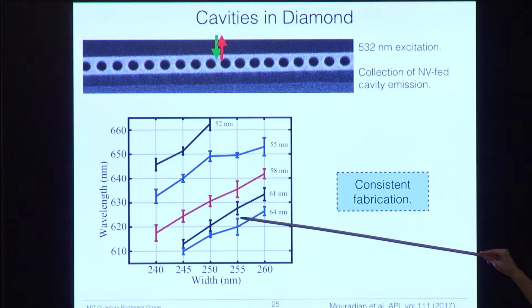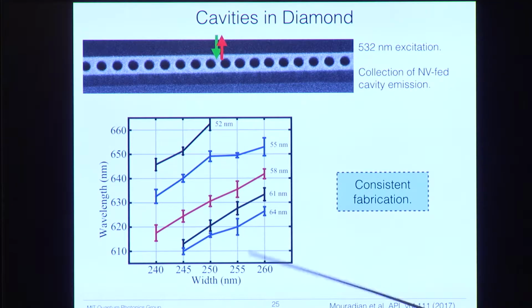And we also see a very small spread in the resonance frequencies, which shows that we have consistent fabrication. And this spread should be small enough to be able to tune with gas tuning any of these cavities to the resonance we want, or any of these cavities that are targeted to be the right wavelength we want.